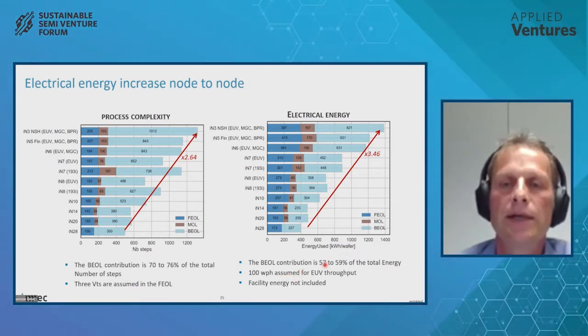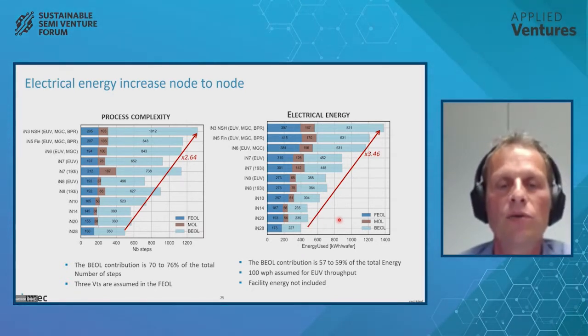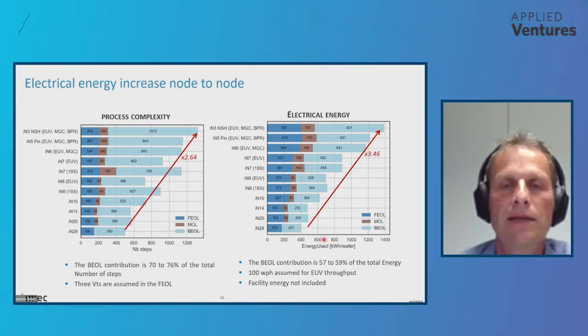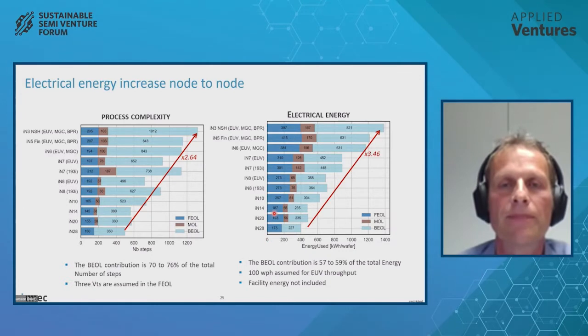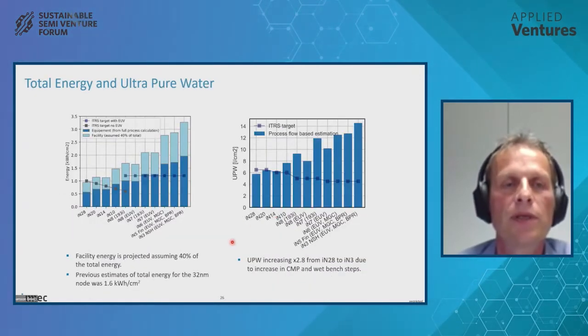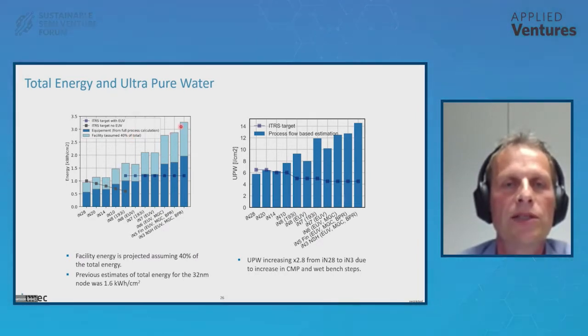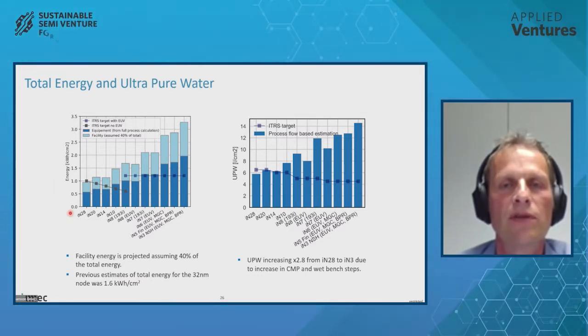There's one thing missing here, and that's the facility energy. So we have counted only the tools, what energy they are using, but not how much the facilities use that actually produce the vacuum and pump the systems and provide the high pressure air, etc. And to do that, we made an assumption in this case, based on other studies, that it's about 40% of the total. So that's this light blue added on top. And then you see the overall energy need per square centimeter for the different technologies.